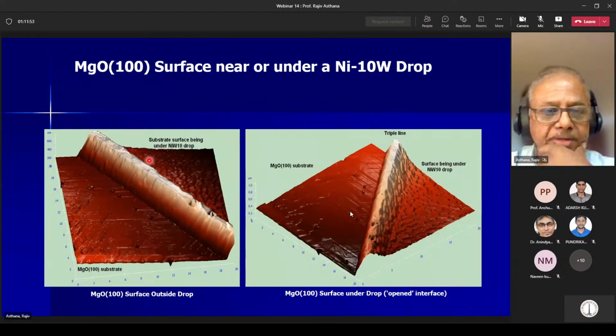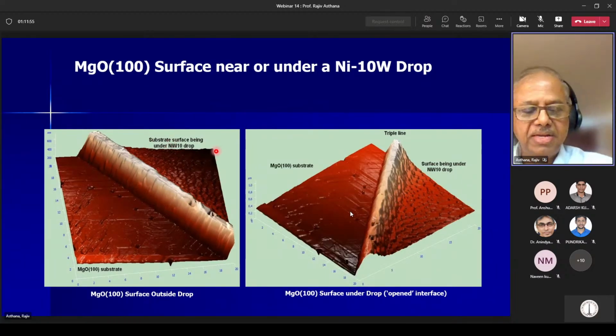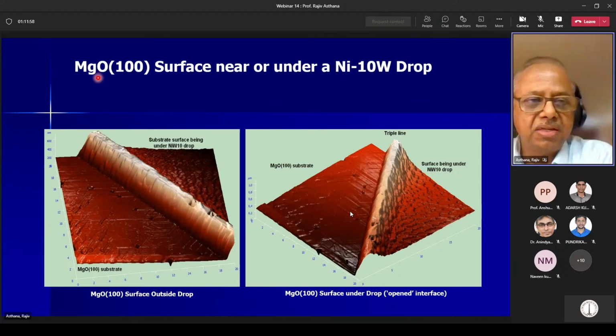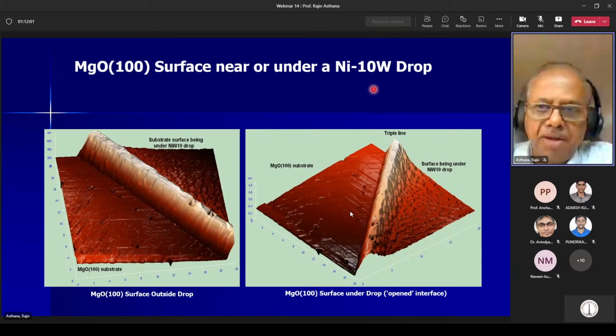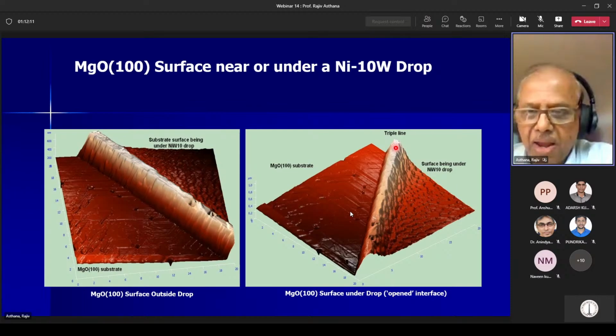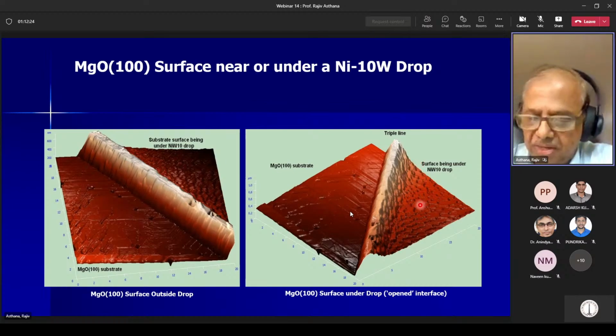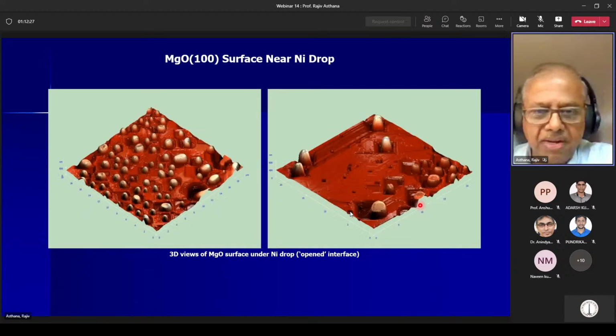Here we are looking at some of the droplet displacement results. So again, this is magnesium oxide surface, and we have nickel tungsten droplet that was on this side, and the droplet was pushed to open up the surface under the droplet. So this is actually the triple line, which was the liquid boundary between the free surface of MgO, and this side was under the droplet. These are AFM images where you can actually see the surface underneath the droplet.